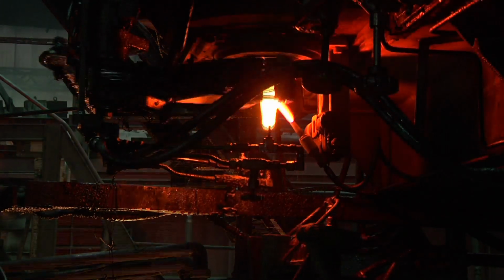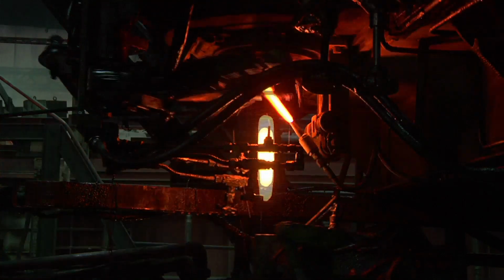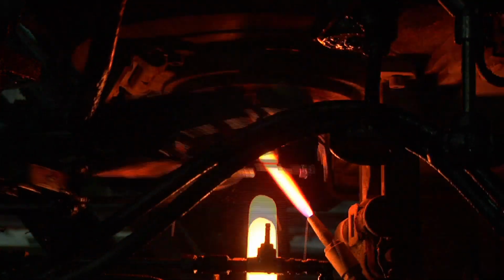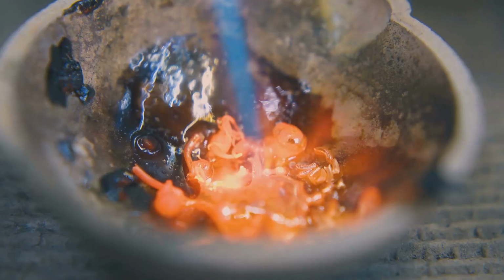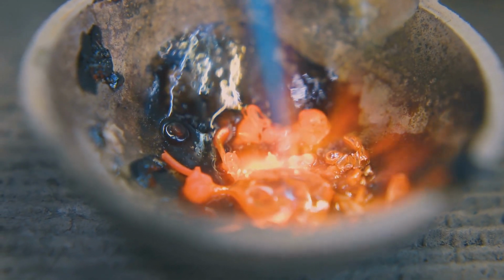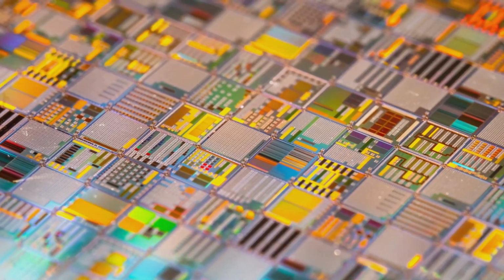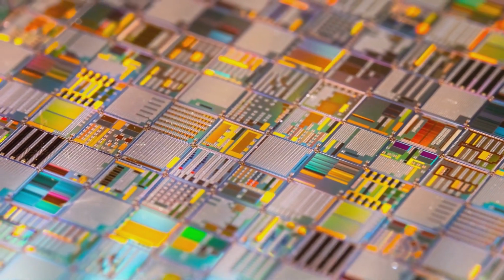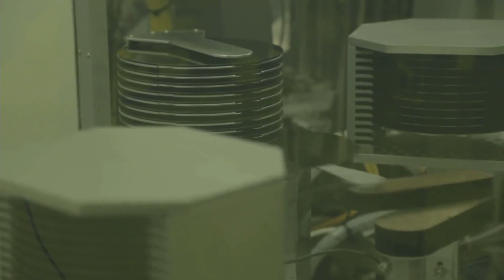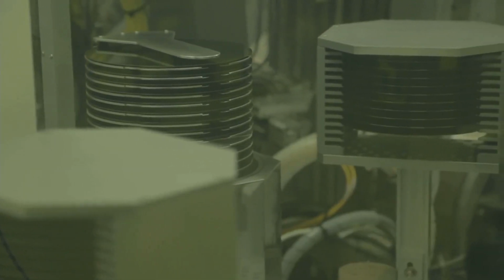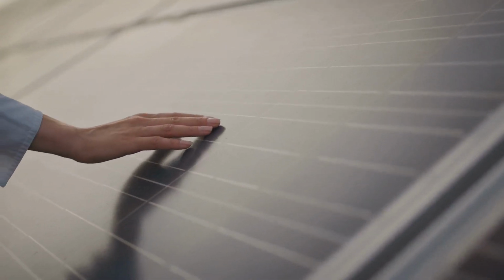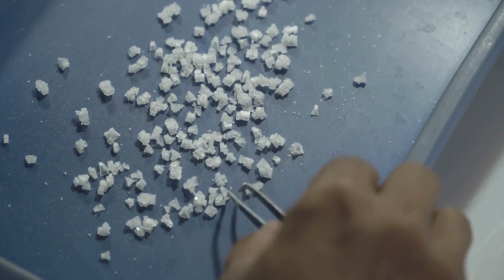Finally, the highly purified trichlorosilane gas is passed over heated rods made of pure silicon. In this hot environment, the gas decomposes. The pure silicon atoms deposit themselves onto the rods. They grow, layer by layer, forming large chunks of polysilicon. We now have solid silicon of incredible purity. These silvery crystalline chunks are ready for the next stage.